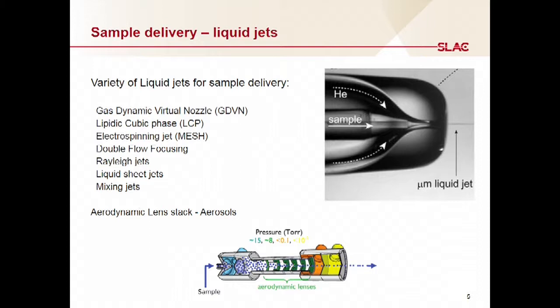that does not like water or whatever buffer that is there, there's a lipidic cubic phase jet, which is typically a slow-moving jet that is typically very viscous, and if your sample is more amenable to that kind of material or that kind of solution, you can use that. There's the electro-spinning jet, which uses kind of electrospray technology to create a liquid jet which is even smaller than the standard GDVN. The electro-spinning jet is very, very good because the jet is so much smaller.